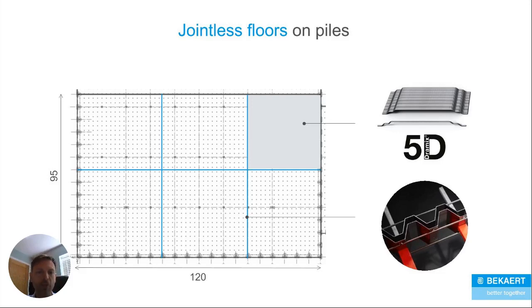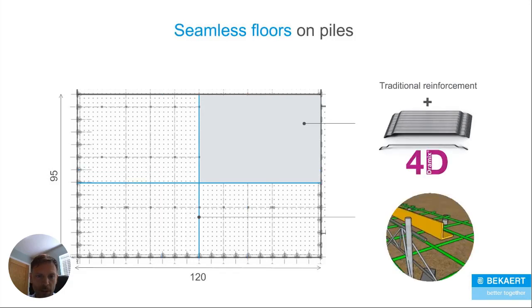Extremely economical. Don't forget, no steel setup beforehand if it's 5D only. It means that the amount of preparation before you actually pour is minimal. The next solution that we have on top of that would be to use Dramix 4D and traditional reinforcement. This is something important to note, that you're not limited to 50 meter long panels, and you're not limited by aspect ratios of your panels. They don't need to be square. They can be long, thin, and in theory, you could even go up to that full 120 meter length in a single day if you could get enough concrete.